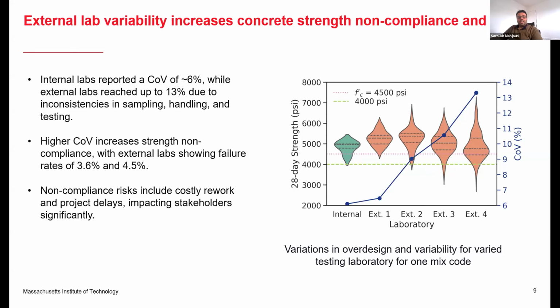We have also investigated the impact of laboratory test variations on the strength over-design and variations, and we could see that external laboratory testing introduces another critical source of variability that significantly impacts concrete strength compliance and risks, and this is a part of the operational variations. Our analysis shows that internal labs report a coefficient of variation of around 6%, while for external labs it can reach up to 13% for this specific mix code due to inconsistency in sampling, handling, and testing procedures.